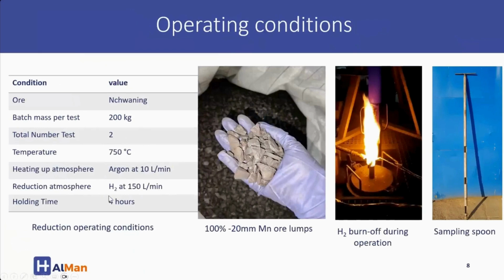During heating up, we purge the retort with 10 liters per minute of argon. Once we reach temperature, we introduce hydrogen, flowing it at 150 liters per minute, and held the temperature for 4 hours.